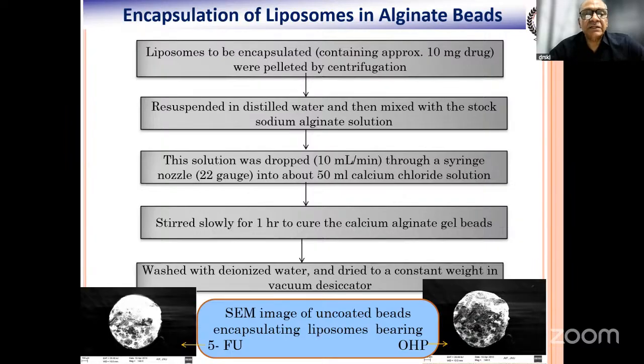In this method, the liposomes to be encapsulated, containing about 10 milligram of drug, are first pelleted by centrifugation, then resuspended in distilled water, then mixed with the stock solution of sodium alginate. This liposome-containing sodium alginate solution was dropped at the rate of 10 ml per minute through a 22 gauge syringe nozzle into a 50 ml calcium chloride solution. The alginate beads react with the calcium ions and convert into calcium alginate, which is solid in nature. It is stirred slowly for 1 hour to cure the calcium alginate gel beads, washed with deionized water, and dried to constant weight in a vacuum desiccator.